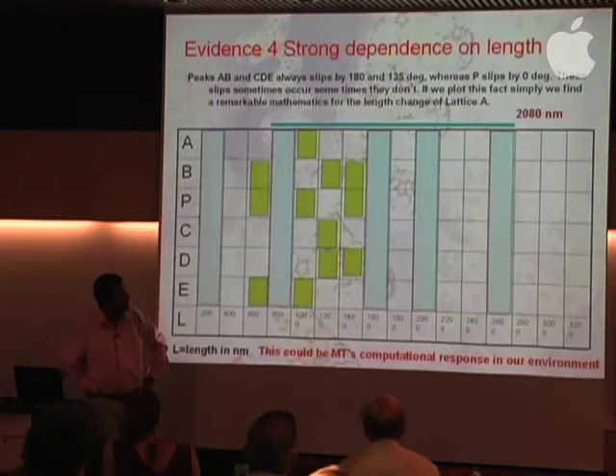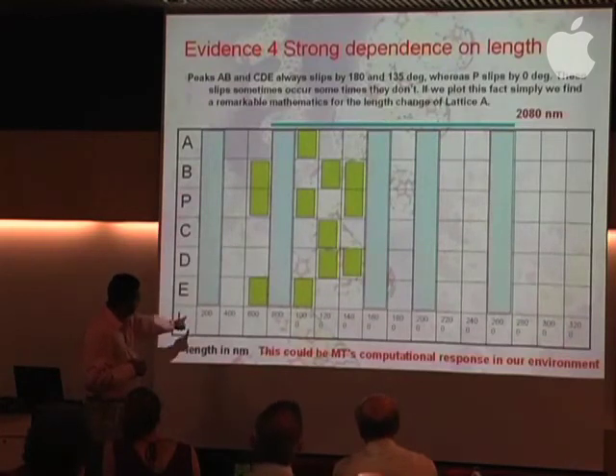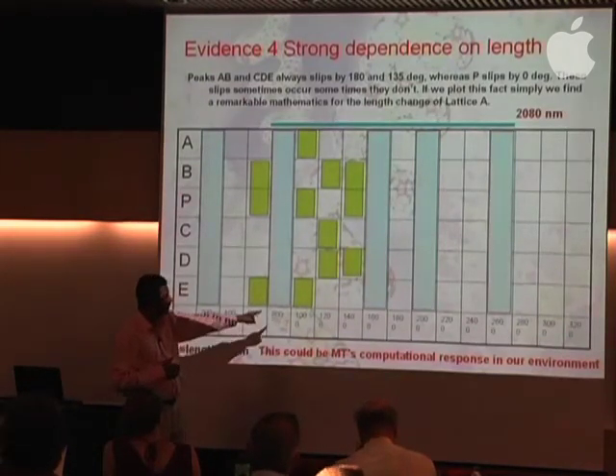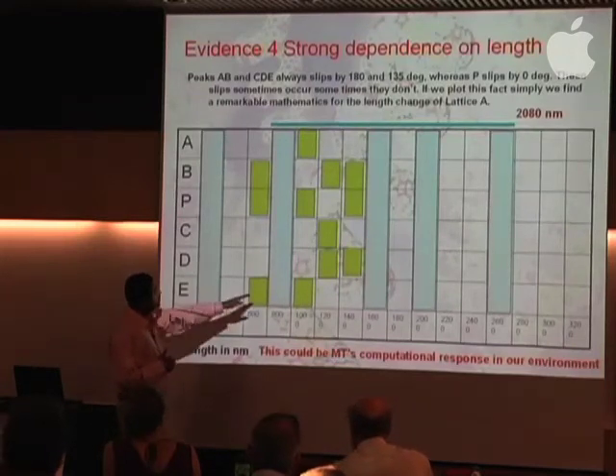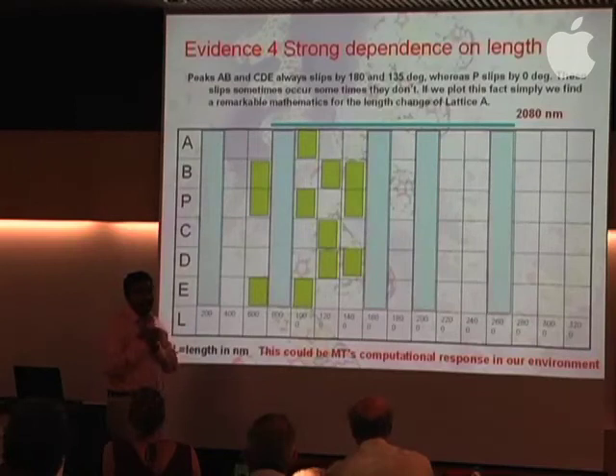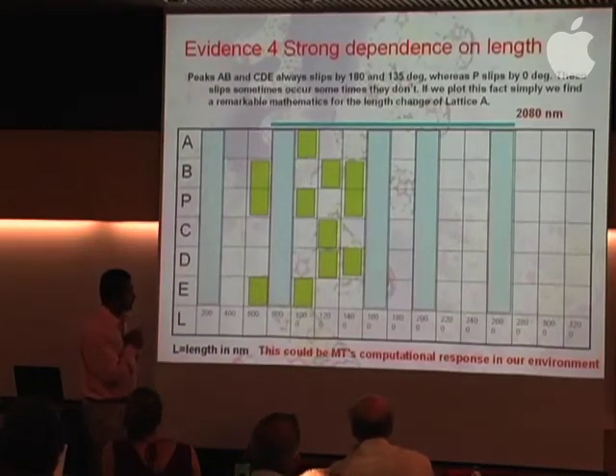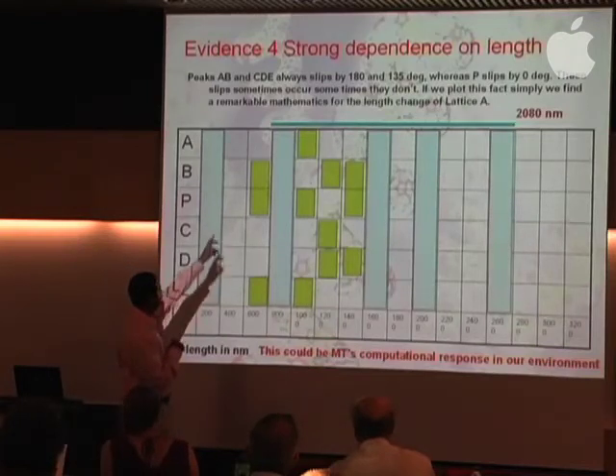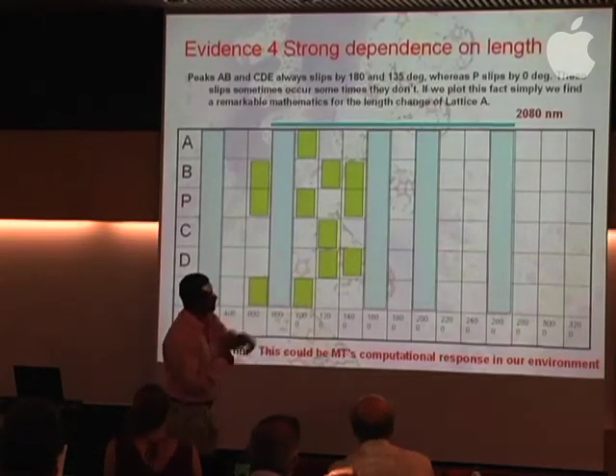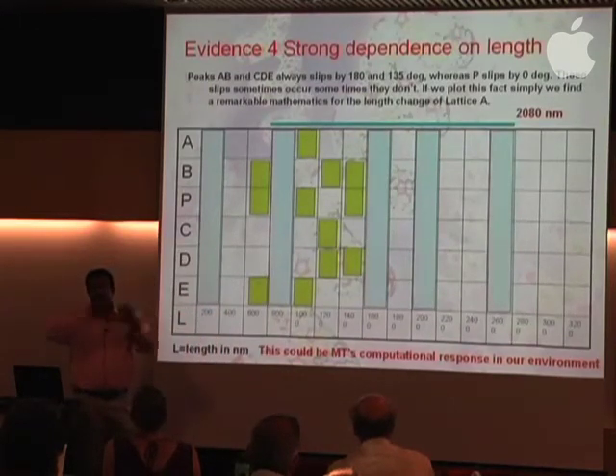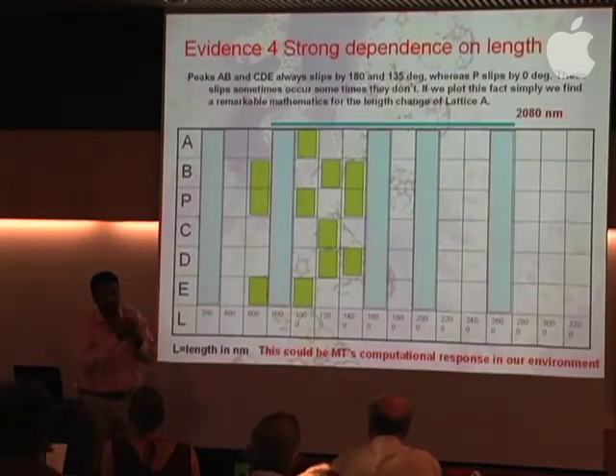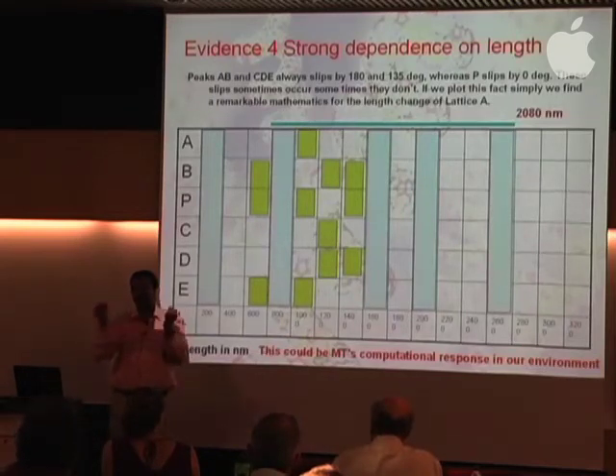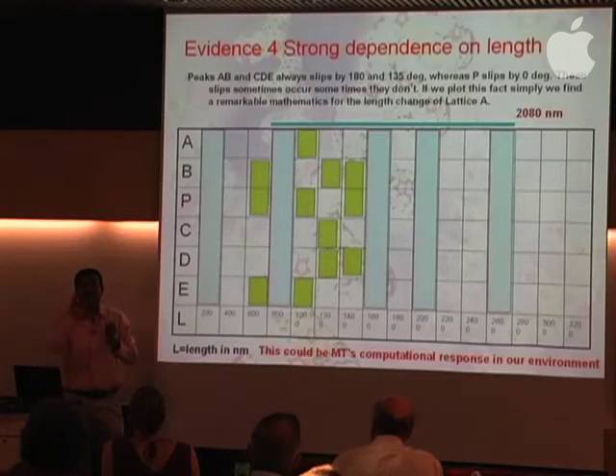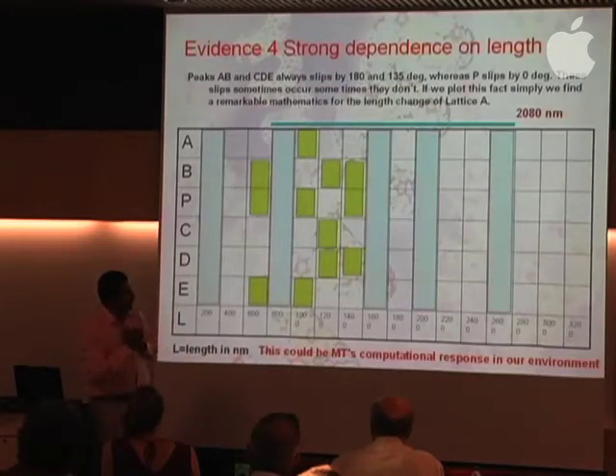Now if you vary the length, we'll see peaks for particular lengths. Length is here, 200 nanometer, 400 nanometer, 600 nanometer, and different lengths. For a particular length, we don't see any phase effect. What happens in those lengths, we don't know, but we can provide information for the other lengths on what happens and which peaks you can see. So even if we forget about everything, forget about the quantum effect, whether it is quantum or not, whether it is entangled or not, if a particular length of microtubule is given to me, I can tell what the phase should be, at which angle, what information will pass through and what it characterizes. So that is one thing.